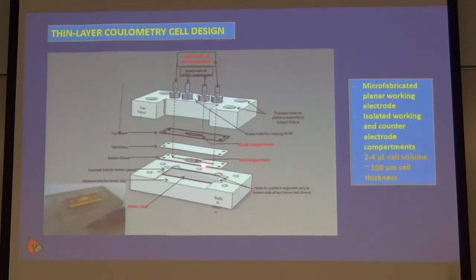So we're going to flow the sample into that compartment, fill it up. We know that volume. We apply a potential to our electrode down here and allow that electrode to oxidize or reduce that entire sample compartment. While we're doing that, we measure the current and convert that to a charge. What are some of the key elements of this? Well, first of all, that cell's not very big. When we make them, they're usually a few microliters in size. Why do we want them so small? Well, if you're going to put this in the field and you ever have to treat your sample, you don't have to add a lot of acid or a lot of base or a lot of some reagent. So you want to have small samples so you can have the possibility of doing real sample treatment in the field.